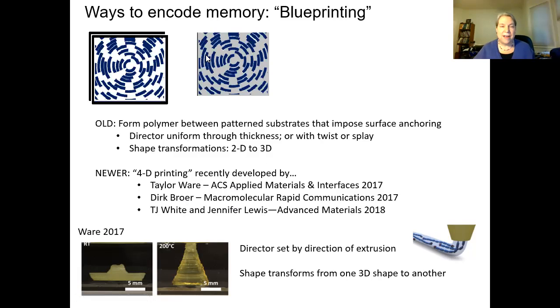So the idea here is simple. Instead of having some sort of patterned substrate, we'll just have a 3D printer that is spewing out the material, and it will polymerize quickly after being extruded. But in this case, the alignment, the nematic director, comes from the extrusion direction. And so then the material is going to shape-transform from whatever you built into something else. And this is an example from Taylor Ware's first paper, where they used the 3D printer and were printing in kind of a spiral pattern, and they built something in the shape of a hat with a brim. And then on transforming, it popped through and made something that looks more conical, standing up. So this brim popped down, and this shape transformation was programmed by the way they extruded it.